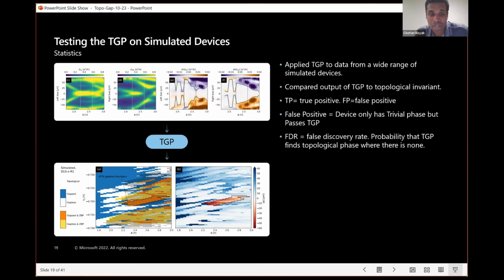The second thing is those disorder regions, what they often have is, you can see sometimes in these figures, you see the zero bias peak comes in earlier before the gap is reopened, before you go into the topological phase. And sometimes these are called quasi-Majorana zero modes, because it's like a precursor. What's happened is the ends of the wire have gone into the topological phase earlier and have stable zero bias peaks before the full bulk phase transition occurs.